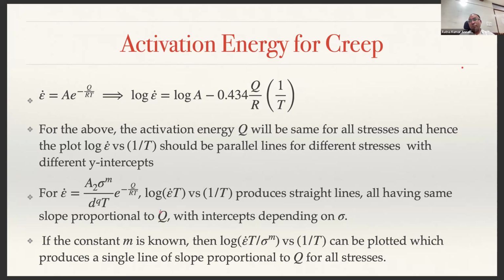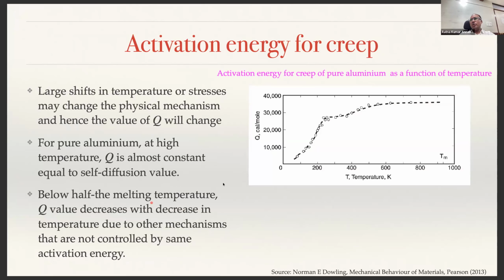So that is how you can actually compute activation energy depending upon your creep law. If you take this creep law, log epsilon dot versus 1 over T will give you Q. If you take this creep law, log epsilon dot T versus 1 over T will give you Q. Okay. So you can see that as the temperature increases, the activation energy increases. Afterwards, it remains constant. This is the activation energy for creep for pure aluminum as a function of temperature.